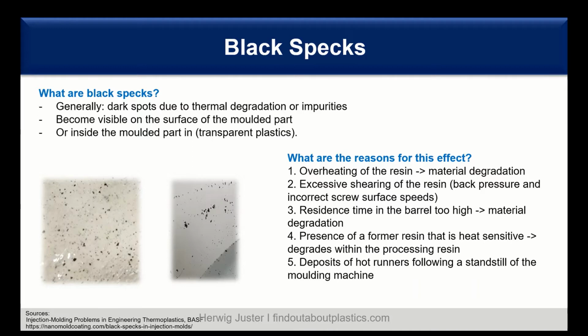It can also happen that you have a former resin in the barrel which is heat sensitive. When you process a commodity polymer and then afterwards a high performance polymer, the remainings of the commodity polymer will degrade, and you have also then black specks. And of course you can also have deposits in the hot runner system. For example, when you switch off the machine or have a standstill of the molding machine, they can develop and then with the next shot get injected into your part.